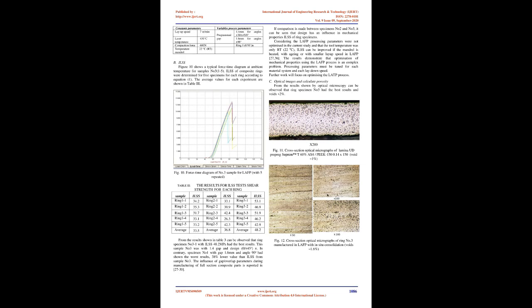Specimens were manufactured with thickness 0.14 millimeters of TPC prepreg. The laminates were obtained by using a laser-assisted fiber placement head, LAFP, produced by Mikrosam, RN Macedonia. Head is attached to a robot arm, KUKA, as shown in Figure 1. The tape head consists of: 1, a consolidation roller, outer diameter of 60 millimeters; 2, a tape feed, guidance, tensioning, and cutting system for UD tape; 3, an optic lens connected via a fiber optic cable to a remotely located 3 kilowatts diode laser heat source and a temperature sensor, pyrometer.